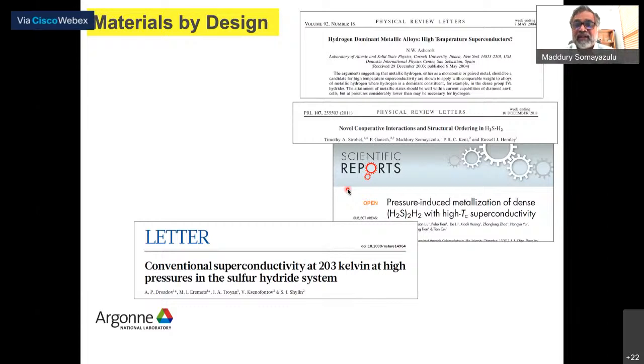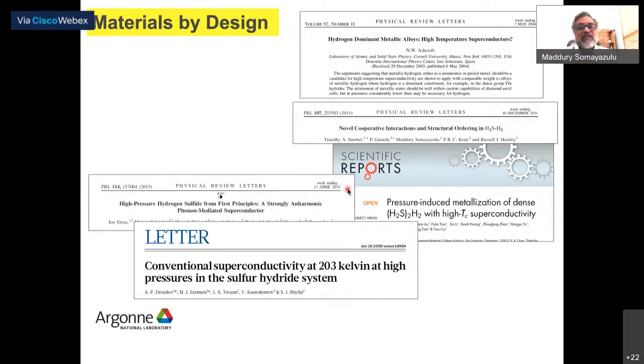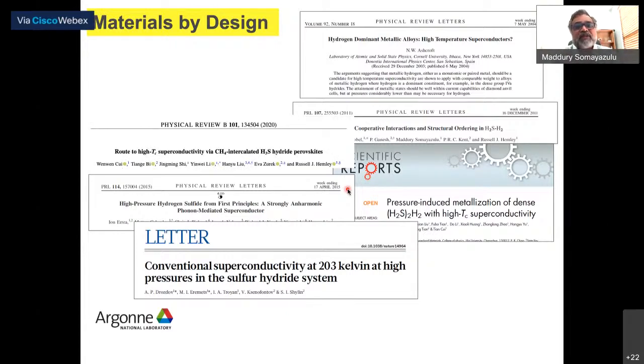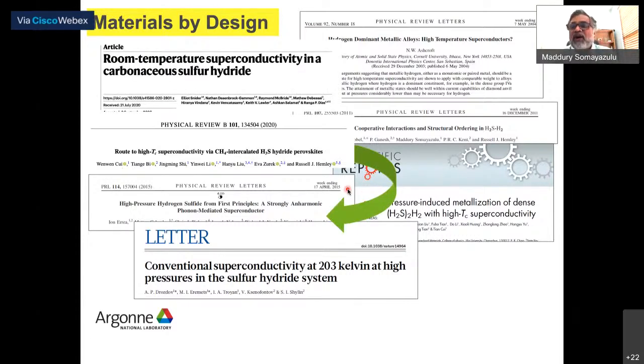Although at that time, people were under the assumption that it was H2S, we now know, because of the consequent calculations by Ion Errea and others, that it's actually H3S, which is a strongly anharmonic phonon-mediated superconductor. So you see the way the interplay has been between experiment and theory in very, very rapid succession within years of each other, due to the maturity in both the experimental and theoretical techniques. And of course, there was then the prediction that you could have a route to higher TC with methane intercalated hydrogen sulfide hydride perovskites. And this was, again, a calculation which came out at that point of time from Geophysical Lab. And you had the culmination in room temperature superconductivity in carbonaceous sulfur hydride.